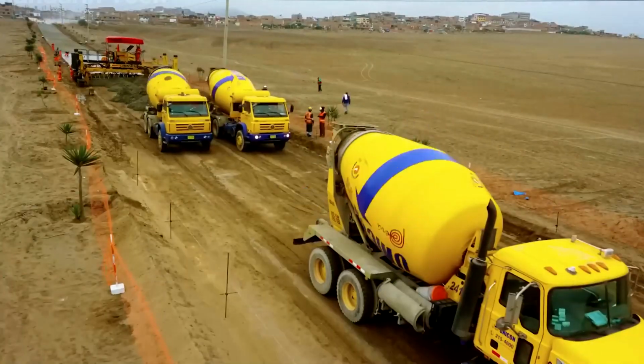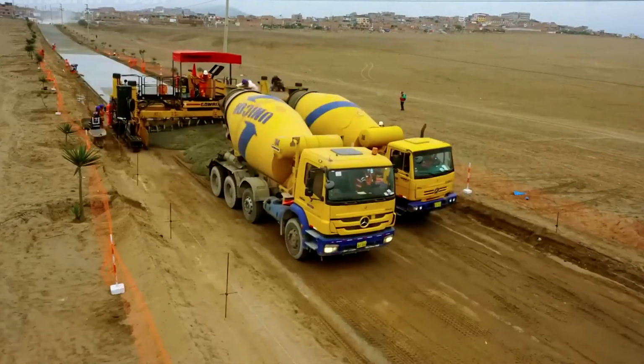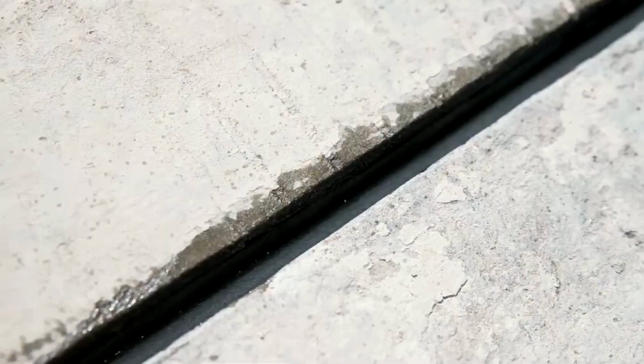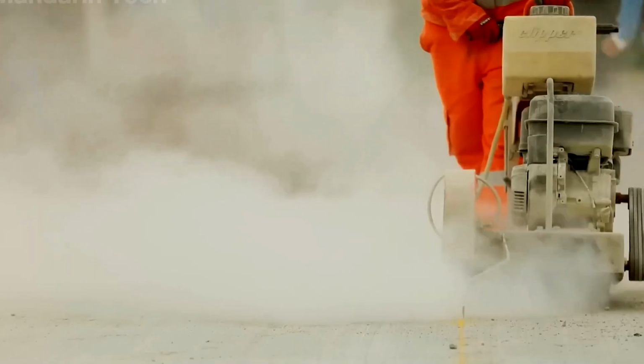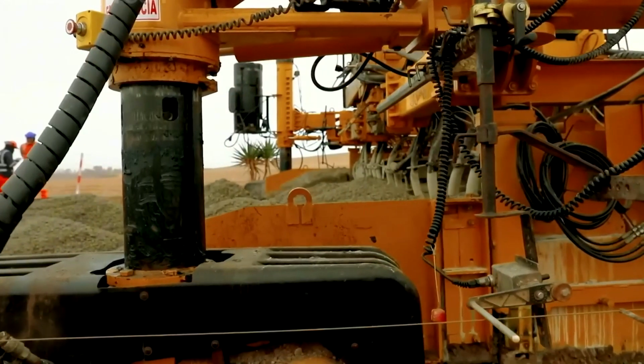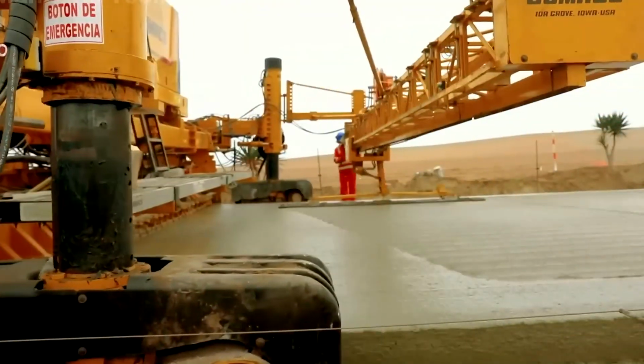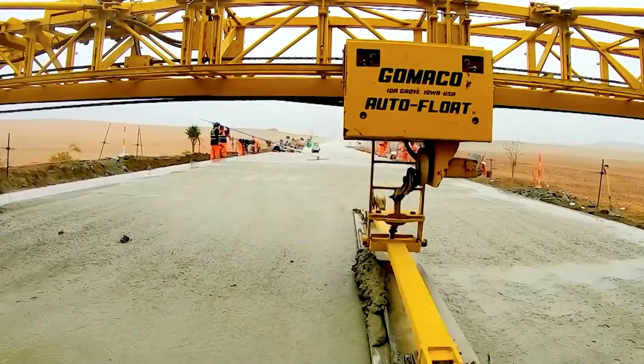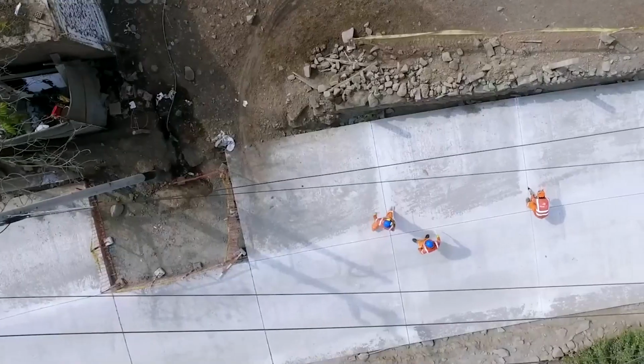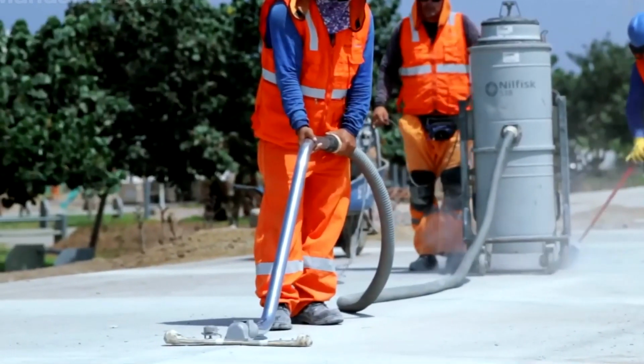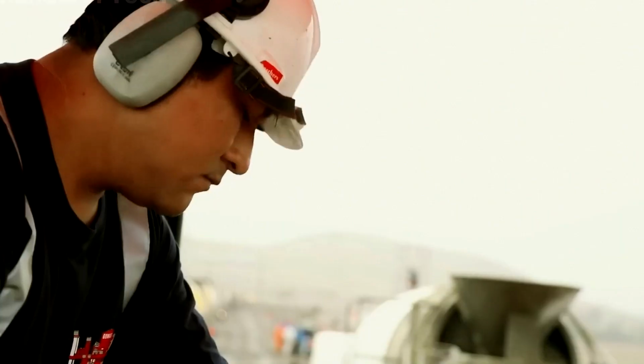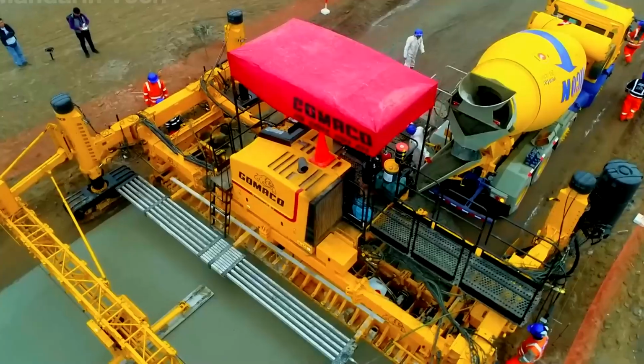A few hours later, once the concrete begins to harden, workers use special saws to create expansion joints at regular intervals. It is visible how the blades cut through the hardening surface, leaving precise lines. These joints allow the concrete to expand and contract with temperature changes without cracking, preserving the surface over time.